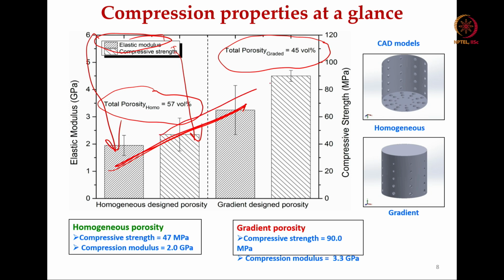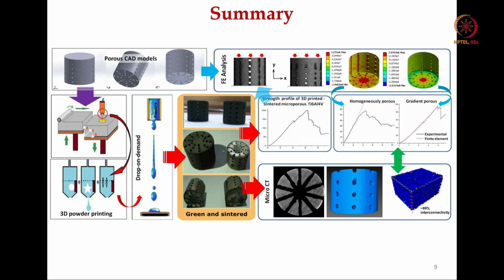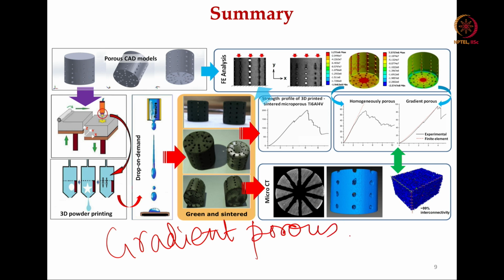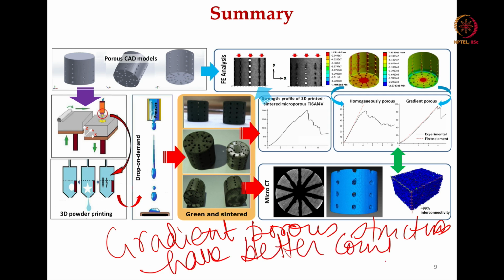If you compare, the strength also clearly increased from almost 47 megapascal to around 90 megapascals, which is more than 2 times strength increase in gradient porous. So, it is very clear that gradient porous structures have better compression properties. That is very clear, right.